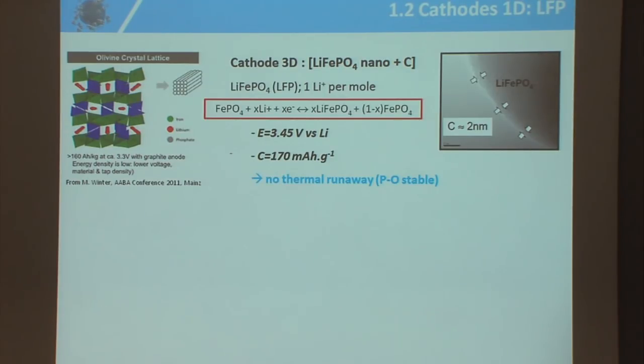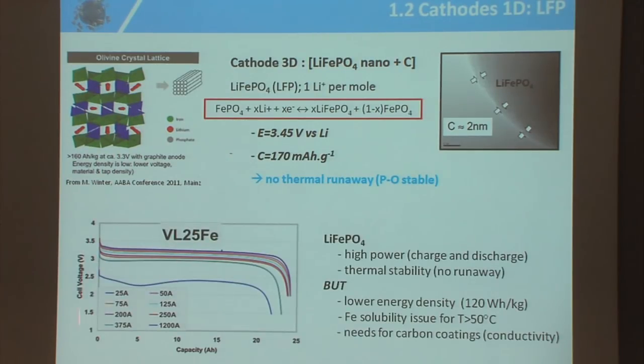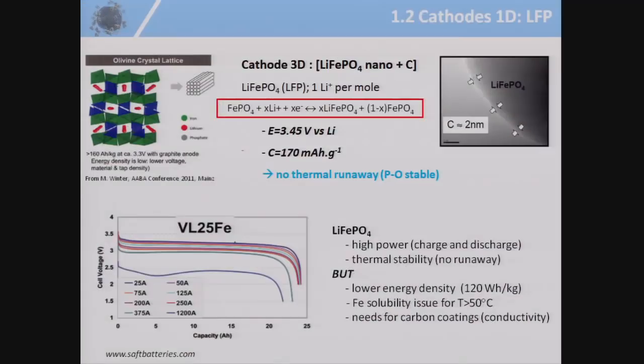Why? It's completely different. Because first, there is no thermal runaway. There are no more cobalt-oxygen bonds. Second, there is a very flat, constant voltage discharge plateau at 3.5 volt. And this is here the cell voltage of an LFP battery versus capacity or time. And you can see the discharge is a very flat voltage plateau. So this structure is very open, so that you have high power because the Li+ ions can migrate very fast inside this electrode. It can be recharged quite fast.